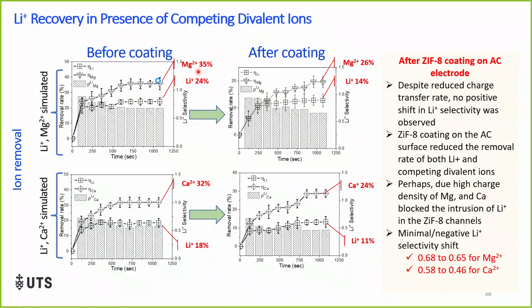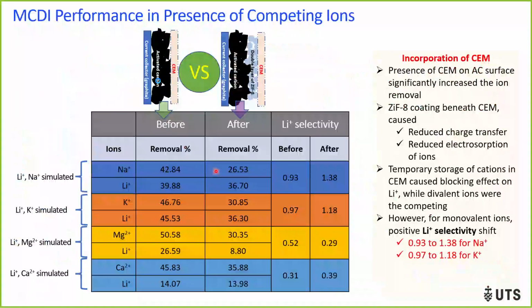Also, we compare with the divalent ions magnesium and calcium. So it changed from 0.68 to 0.65 and 0.58 to 0.46. So when you have divalent ions, lithium selectivity was not really high compared to the monovalent ions. So this is the summary of the competing ions with the lithium and sodium and the lithium and potassium: after coating, lithium selectivity increased, but for magnesium and calcium overall it decreased.